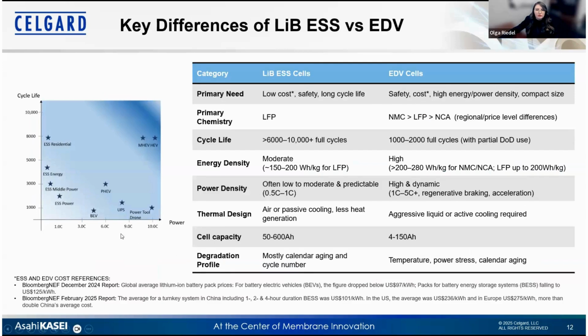Here's a short overview about the key differences between energy storage cells and EDV cells. The primary need remains cost for both of them, but partially more for ESS since the cell capacities become larger and larger. There are now announcements of energy storage cells with over 600 ampere hours and even up to 1,175 ampere hours of capacity per single cell. And with that, this impacts manufacturing yields and cost more dramatically than for EDV cells.